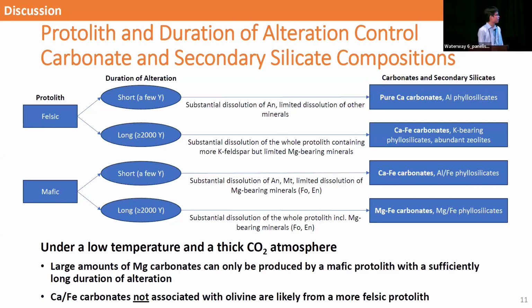We found that under a low temperature and a thick carbon dioxide atmosphere, large amounts of magnesium carbonates can only be produced by a mafic protolith with a sufficiently long duration of alteration. We also found that calcium iron carbonates that are not associated with olivine are likely the result of a more felsic protolith.